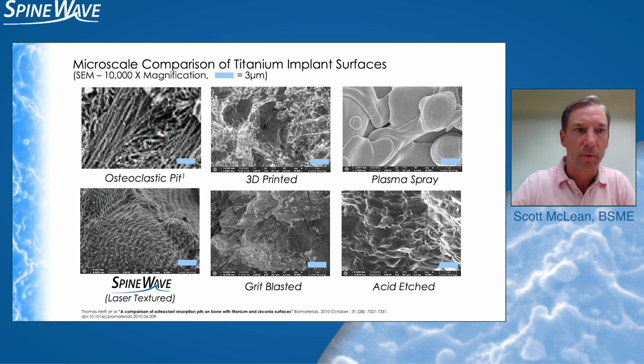So the next magnification we're going to look at is 10,000x with scale bars of 3 microns. And this is a useful magnification to look at the ridges on the SpineWave surface intended to replicate the collagen fibers in the osteoclastic pit. And again, looking at the competitive surfaces, while there's again plenty of roughness, there's just nothing organized in that sort of manner to mimic the collagen fiber.